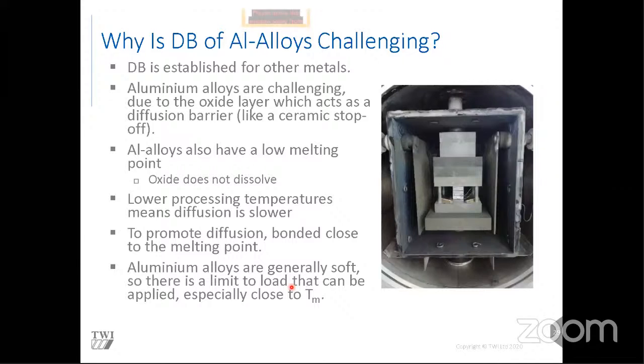Firstly, diffusion bonding of aluminium is challenging, but diffusion bonding for other materials is well established. The reason it's difficult for aluminium is because of the oxide layer, but you're probably asking yourself, don't other materials also have oxide layers? That is correct, but there's a difference here. Because aluminium alloys have a low melting point, you cannot heat the material to a high enough temperature to dissolve the oxide. In doing so, you would melt the aluminium, which is useless. So that's the problem we're trying to overcome.